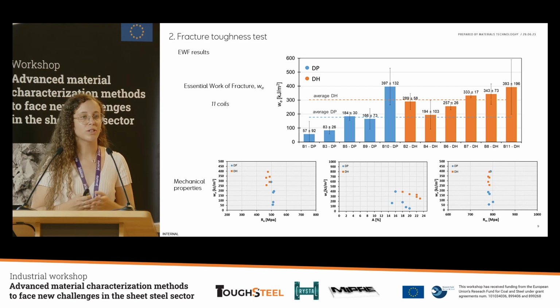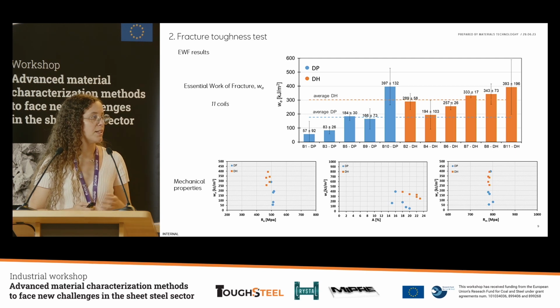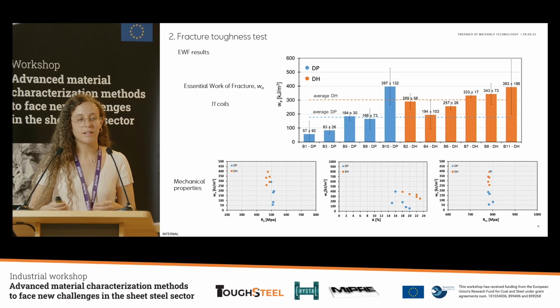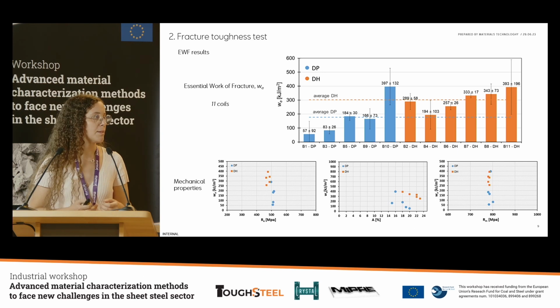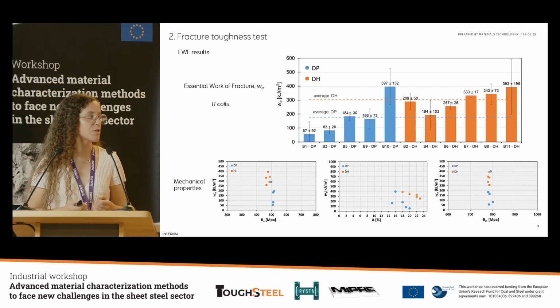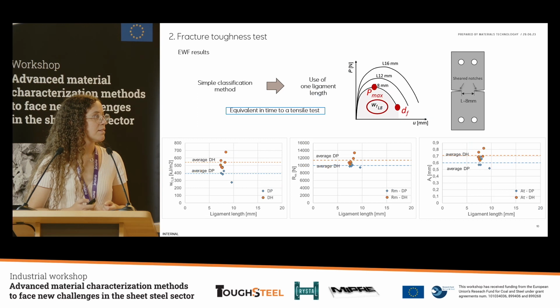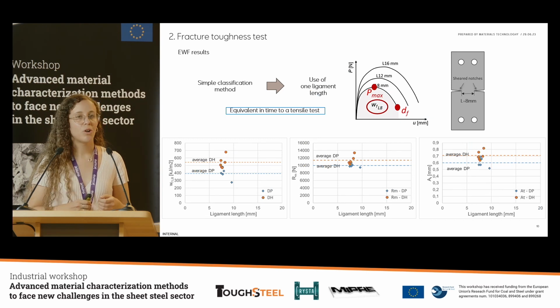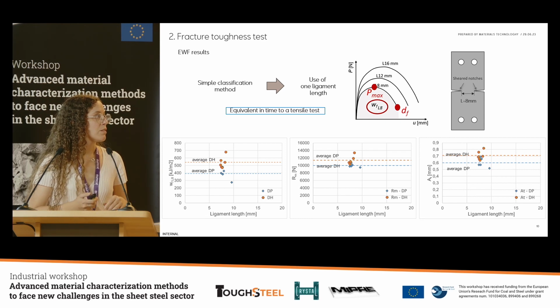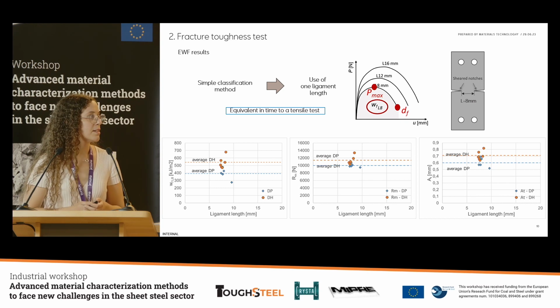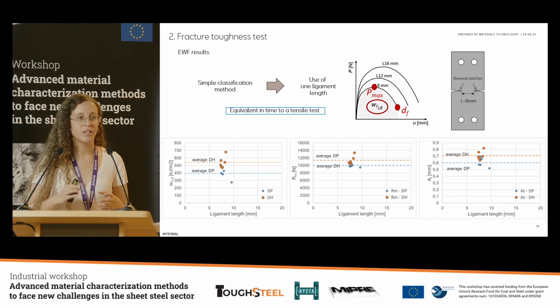In this case, we used a range of 8 or 10 specimens for each material, but we want a faster method that can be applied easily in the industry. Then we decided to use only one ligament length to at least classify the different coils and their fracture behavior. What we use is this single ligament length of 8 millimeters, and we measured different parameters.